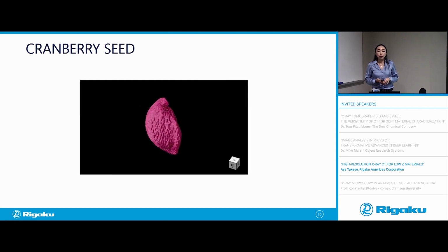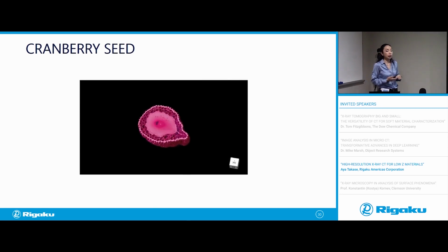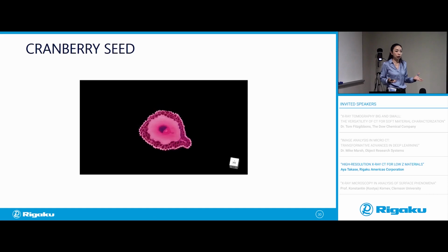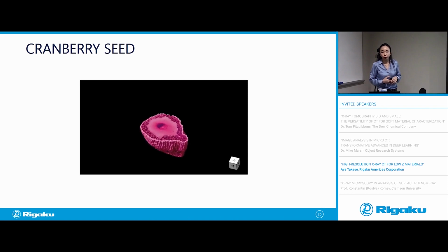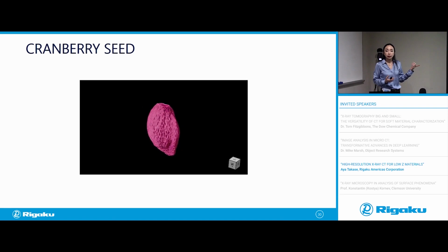This one is a cranberry seed. The seed is probably about 2-3 millimeters in size. And the whole thing is, again, organic, doesn't absorb a lot of X-rays, but this was a scan with copper radiation, and you can get a really high contrast image of organic materials like the seed or grains. What else? We've seen cereal as well, so you can see all those things with X-rays.